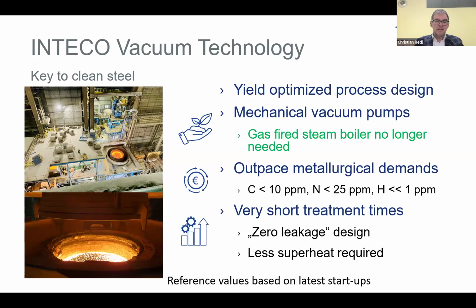The metallurgical results you're reaching, so you can produce steel grades with 10 ppm carbon, nitrogen content of 25 ppm, and hydrogen content of 1 ppm is usually a target for some. As Mr. Ahmed said, the limit for the specification is sometimes 2 ppm, but of course you tend to be below this to have a very good product. To reach very short treatment times, of course, you have to ensure that your plant is tightly sealed, so you have an effective vacuum treatment.